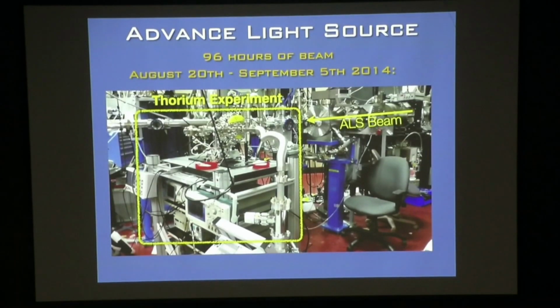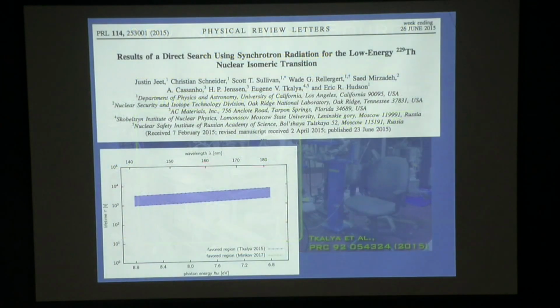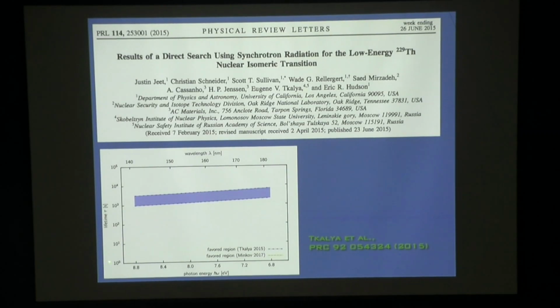All right, and so this was our limit plot, or our exclusion plot, we called it. So on this axis is the possible wavelength. Here's 140 to 180 nanometers. On this axis is the lifetime. This blue region is sort of where we thought this should be with what I would say 90% confidence. It's kind of hard to say a confidence interval when you're putting together a lot of different experiments, but it's a reasonable kind of estimate of where the transition should be.